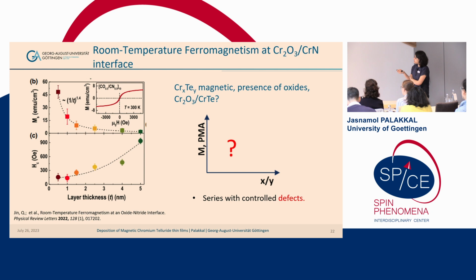And here, interestingly, I would also like to show this graph. Such interfaces, oxide-nitride interfaces, are also showing room temperature ferromagnetism. This is a chromium oxide and chromium nitride interface, and this is just because of the electronegativity of the two phases. There will be a charge transfer between these two cations, and they provide sufficient exchange interaction, and they are showing the magnetism. So this can also be the case for chromium telluride material, and we are not yet sure of the origin of the magnetism in this material, and that's what we are focusing on: a series of samples with controlled defects, because defects are also important sometimes. The point is that we have to control it.